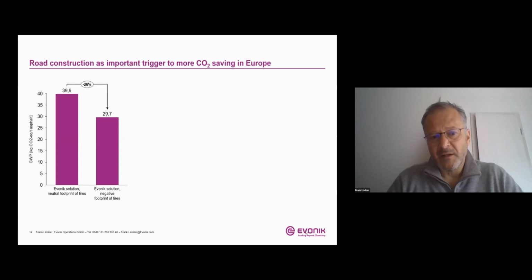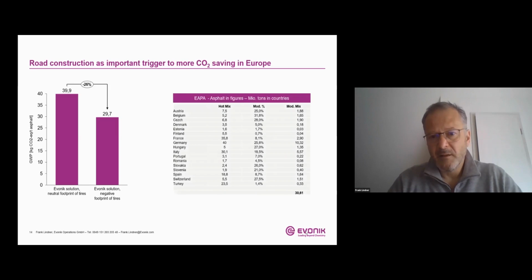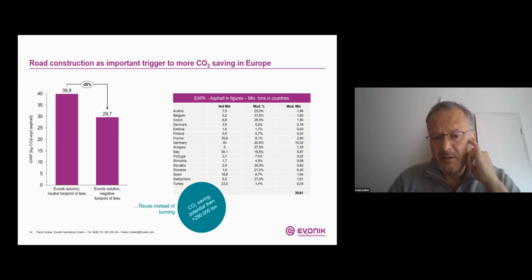First of all, we can see that there is an impact from using rubber, and that is coming from not burning. Not burning the tires is saving 700 kilograms of CO2 for every 1 ton of tire which is going into recycling. We then see the asphalt figures, as we can see on the upper side. We know how much modified asphalt is produced in Europe in the countries which are listed. And if we take this as a basis, then roughly 290,000 tons of CO2 savings is possible